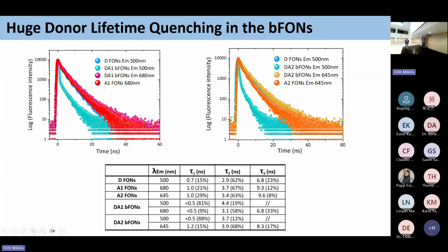And the decays you see have a multi-exponential shape, but this reflects the micro-heterogeneity of a nanoparticle sample. The most remarkable evidence we can find from this data is when we collect at the maximum of emission of the donor in the binary nanoparticle. We see that there is a huge quenching in the donor lifetimes. That suggests a very rapid, efficient energy transfer within the binary nanoparticles, with the lifetimes seeming to be dominated essentially by the lifetimes of the acceptors.